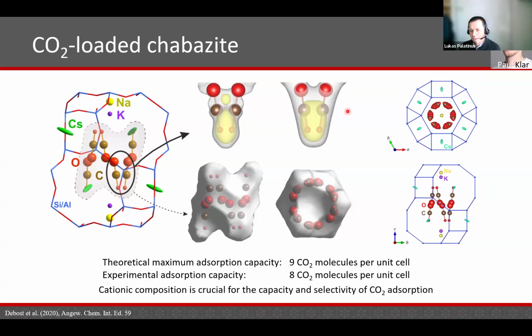We could calculate that there are at most 9 CO2 molecules that can be absorbed per unit cell of the material. And indeed, the experimental absorption capacity turned out to be about 8 CO2 molecules per unit cell. So very high absorption capacity experimentally, very close to the theoretical limit. And that was, of course, possible thanks to the nanocrystalline nature of the material. So the surface to volume ratio was very high.